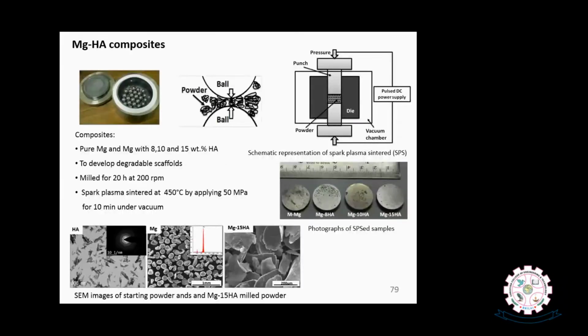Quickly, we'll see a couple of slides on magnesium-based composites by powder metallurgy route. We have adopted ball milling, where we mixed the powders of magnesium as well as calcium phosphate ceramic phase, what we call hydroxyapatite, for biomedical applications. We have done 20 hours of ball milling at 200 RPM. And we have done spark plasma sintering of these ball milled powders at 450 centigrade by applying 50 megapascals load for 10 minutes in vacuum.